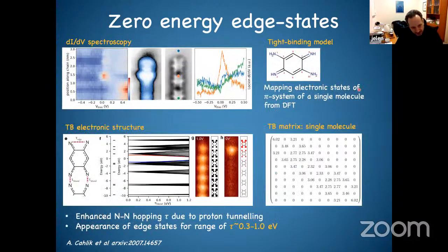For that, we calculated the chain. We took the p orbitals in the chain, and normally they are very weakly coupled, so there is no electron tunneling through this coupling between the unit cells. So this is the matrix of the single molecule. Now what we will do is make a chain tight-binding model, and we will play with these intermolecular hoppings, which normally in DFT are very low. But now there is a proton transfer going on here.